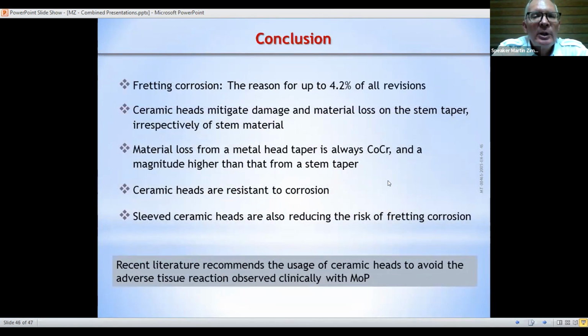This brings me to the conclusion of my second part of the presentation tonight. You have to know that fretting corrosion can be the reason for revisions in up to 4.2%. Ceramic heads mitigate damage and material loss on the stem taper, irrespective of the stem material. The material loss comes mainly from the taper of the head. And if you speak about cobalt chrome, you have a high magnitude of material loss and you are creating chrome and cobalt metallic debris in the body of your patient.